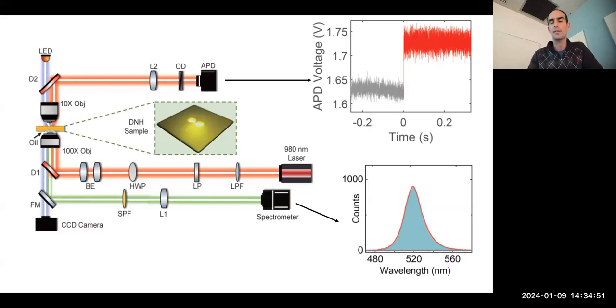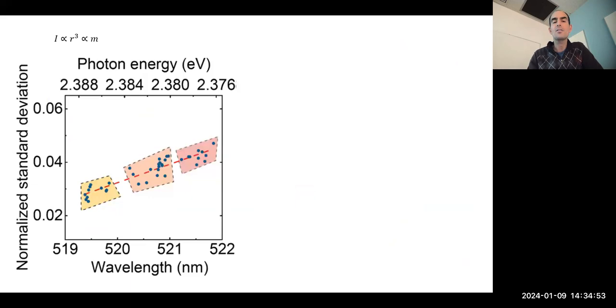It's thermal fluctuations of the particle, and from those thermal fluctuations we can figure out the size, because it's related to the Stokes drag - the hydrodynamic drag is related to particle size, as is the amount of optical scattering. From that, we can relate the size of the particle to its quantum confinement. When you make a particle smaller, the energy blue shifts, so you get shorter wavelength emitters.